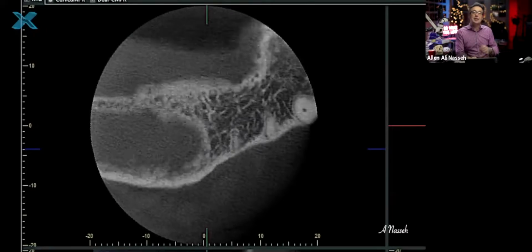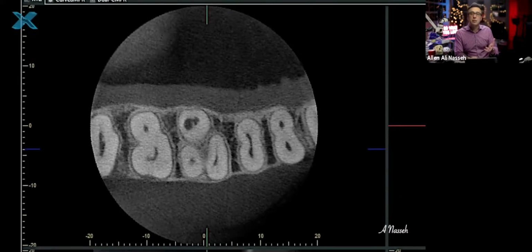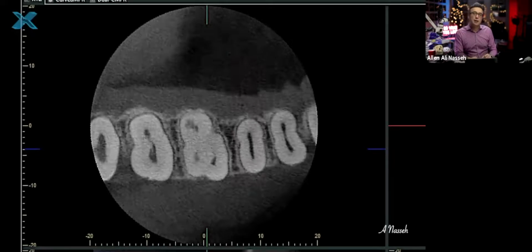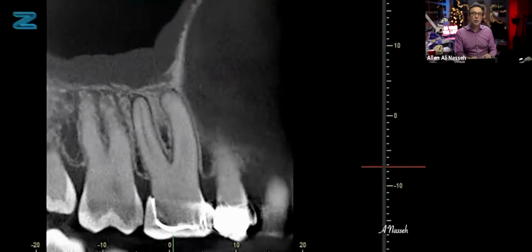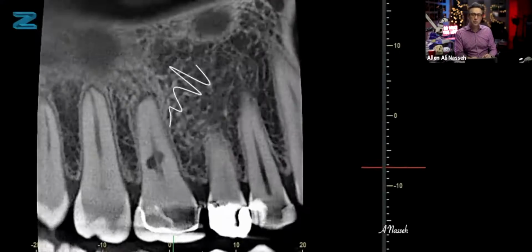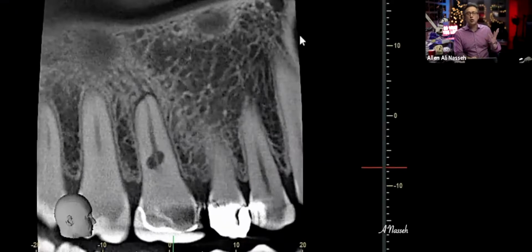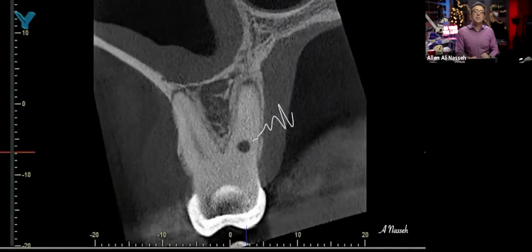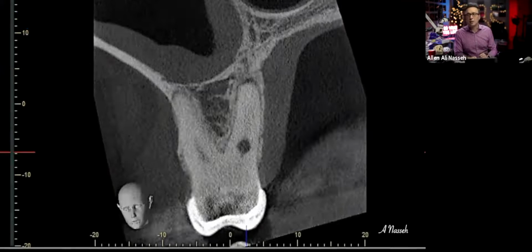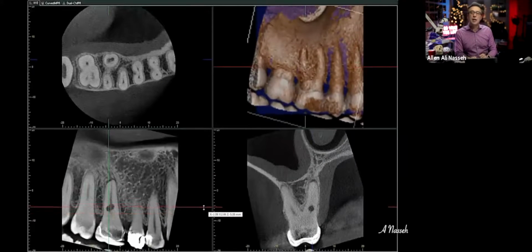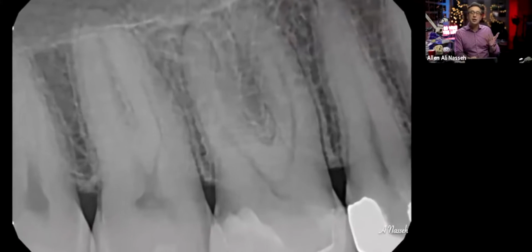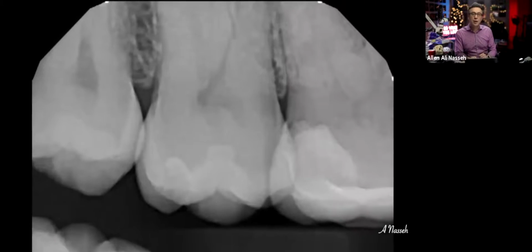But now we can see that the crown had decay under it, and it had caused some internal resorption. As you can see here in the palatal root, you can see that defect on the palatal root. As we know, internal resorption is, in some cases, related to some persistent coronal inflammation that is present in these canals. And you can see that the regular PA x-ray was not showing it, but it was really the CT that allowed us to see it.